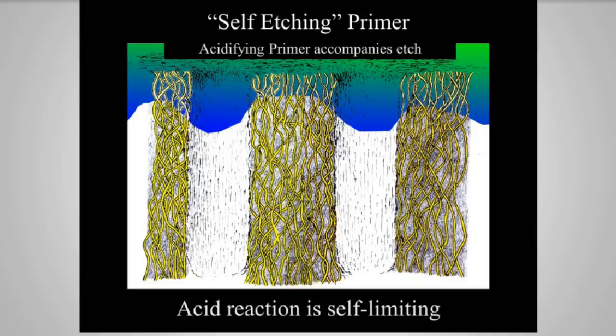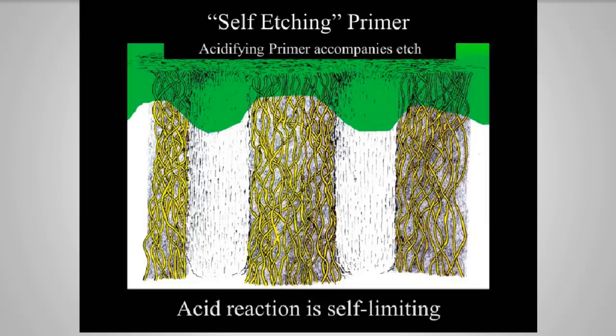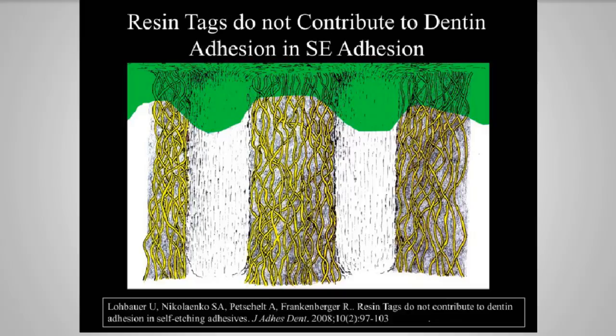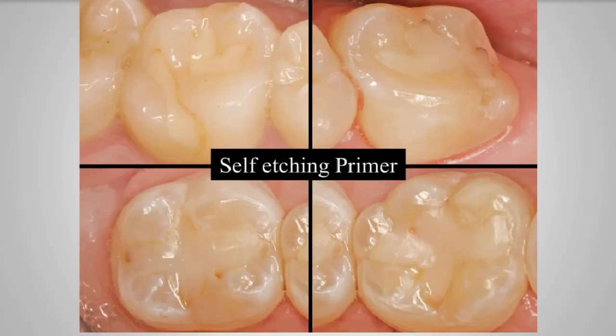But as you can see, what a great system, because you've never left the dentinal tubules open, because it accompanies the etch down in there. And then when the acid is used up, it has no ability to leach hydrogen ions. It just remains there in place, and we have the seal. It's interesting that the resin tags may not contribute as much to adhesion with the self-etching systems.